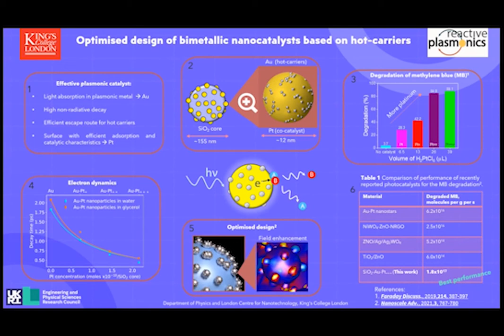As a benchmark, the degradation of methylene blue was studied. It was found that the reaction is very sensitive to platinum on the structure, increasing as the platinum loading increases up to a certain point. The optimal design consists of gold particles fully coated with a platinum layer, along with platinum nanoclusters at the surface.